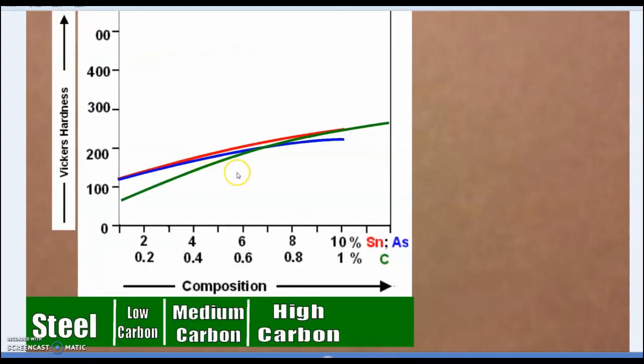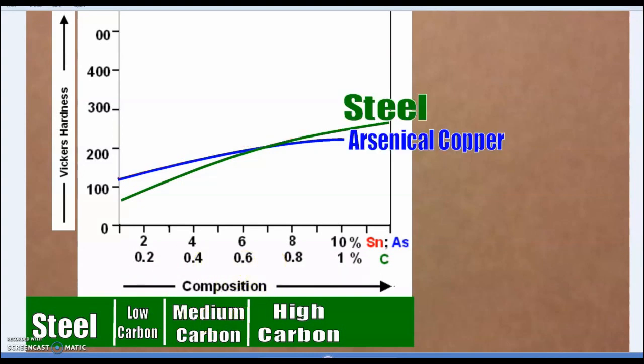So there we see a line comparing. There's the steel, the blue line is the arsenic bronze, and the red line is the tin bronze. And just to help out, C is carbon, so iron plus carbon is steel. Very small percentage. If you're over 0.6% carbon by weight, the steel is high carbon or hard steel. Medium or low carbon steel is below that, of course.